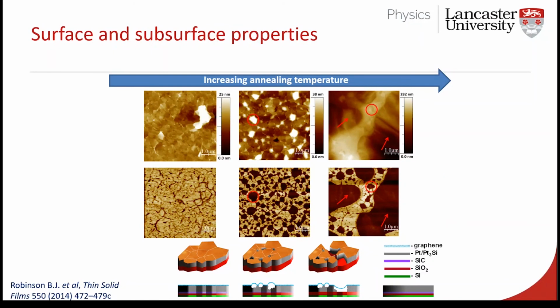And across the top line here, you see these three figures, 1, 2, 3. We see the topographical, so the surface profile of what's going off there. And that's a bit weird. It's a bit interesting. Definitely, there's a change in structure as a function of annealing temperature. But how can we tell what that means?